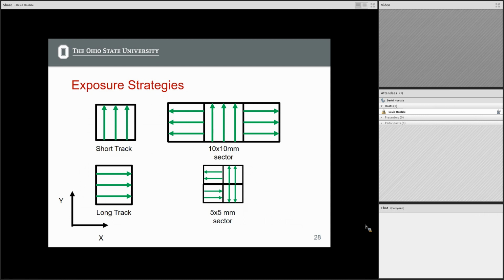So they tried 4 different scanning strategies. The short track method, which was scanning along the width of the part, so along the short side. The long track, which was scanning along the long side of the part. And then these different sector scanning methods, which they called the island methods, where they had a 10 by 10 millimeter sector and a 5 by 5 millimeter sector.